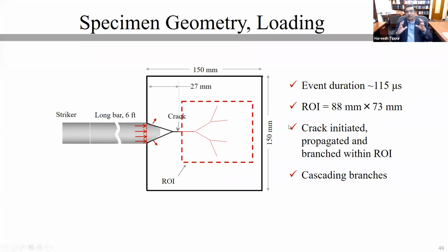As a result of our limited ability to capture the region of interest, in this case, we wanted to keep the region of interest the same without modifying things a lot. So we moved the region of interest a little bit into the specimen itself. So the event duration is same, region of interest is same. However, we are able to see the details associated with not only the first bifurcation, but another pair of bifurcation, which happened at the end of your region of interest.